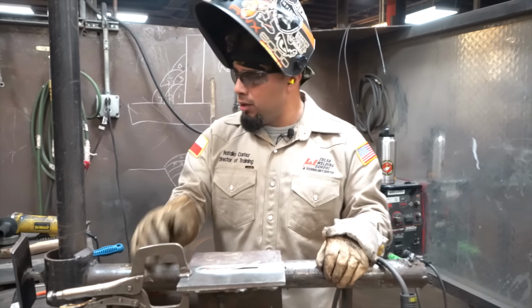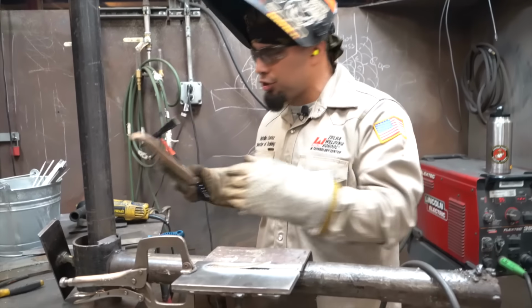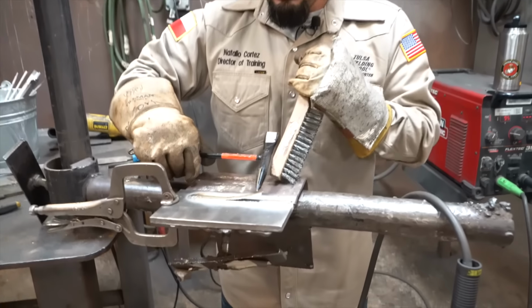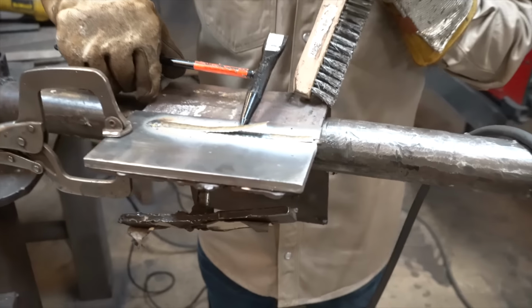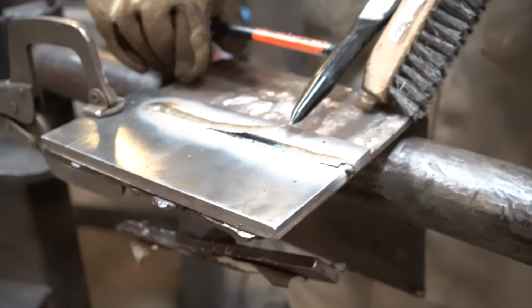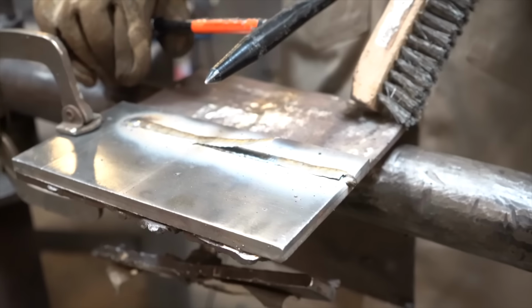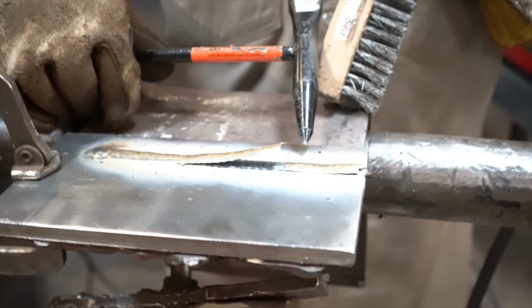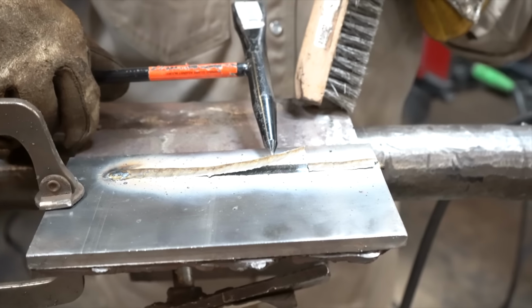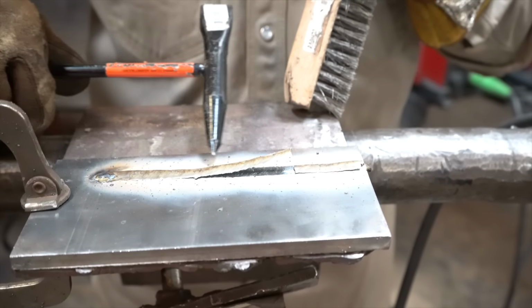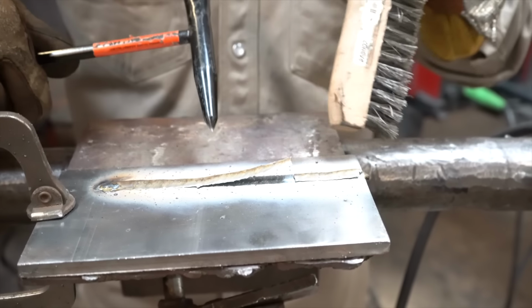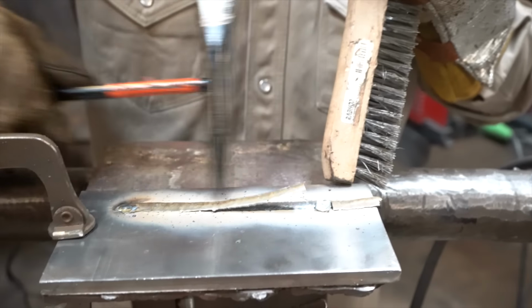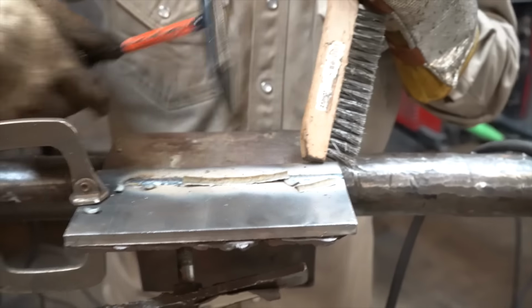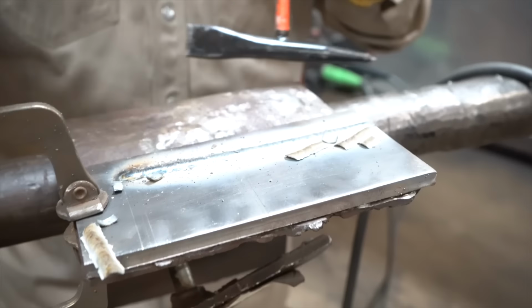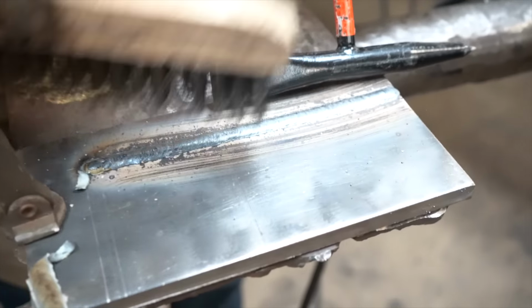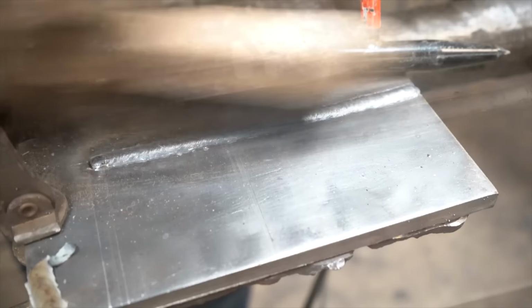We just ran our first weld. Gonna grab our chipping hammer and wire brush, knock off the slag. A lot of welders love it when this happens. What this means, if the slag starts to come off by itself, it means that you have the right speed, the right arc length, all the way down your weld. Okay, holding down the workpiece, going on this edge, knocking off the flux. Switch over, hold it down with the wire brush.